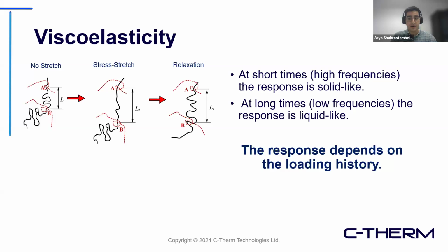At short times or high frequencies, the response is solid-like, and at long times or low frequencies, the response is more liquid-like. Please keep these 2 points in mind. I'm going to explain more in detail about these 2 sentences, but keep in mind that the response depends on the loading history.